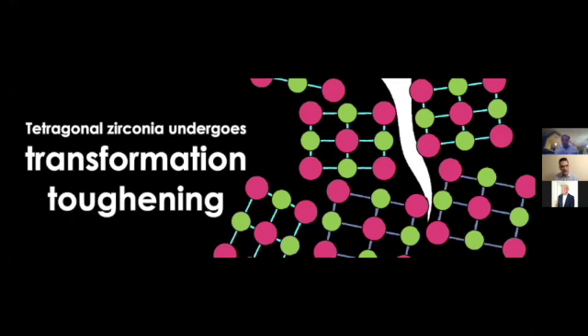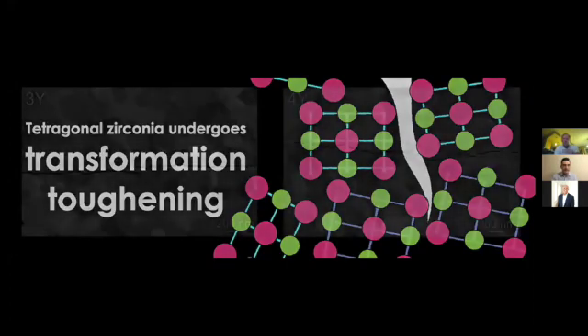And Alumina doesn't do this. It's not done by glass ceramics. It's something that's only done with the tetragonal zirconia. And I've seen some people talk about reinforcing materials with particles of zirconia. I think the material has to be a polycrystalline zirconia with all zirconia. If you try and reinforce with something with zirconia, it's not going to have the magic because the cracks will just go through the other phase. They'll skip the zirconia particles. So that's kind of the magic of tetragonal zirconia.